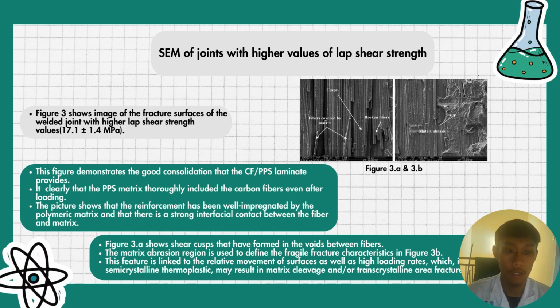SEM of joint with higher values of lap shear strength. Figure 3 shows an image of the fracture surface of the weld joint with the higher lap shear strength value, 17.1 plus minus 1.4 megapascal. This figure demonstrates the good consolidation that the carbon fiber over polyphenylene sulfide laminate provides. It clearly shows that the PPS matrix thoroughly includes the carbon fiber even after the loading. The picture shows that the reinforcement has been well impregnated by the polymer matrix and that there is a strong interfacial contact between the fiber and matrix.